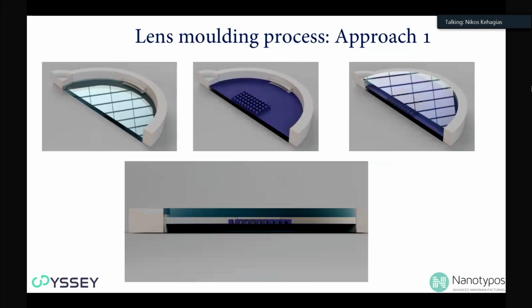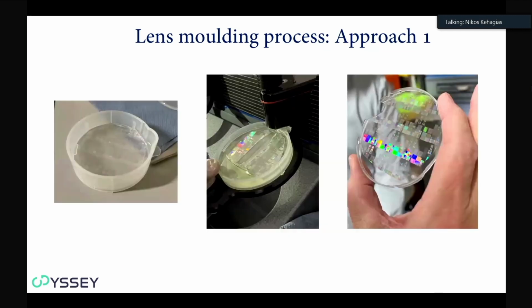This is just a cross section of having 2 glass molds, our patterned film, our working mold, inside which has a spacing, so we can control really the thickness and correct and replicate by this simple molding technique the nano features on our UV curable resist. So this is just some images of the process, how it was filled, the rubber ring, and how we are filling in the UV material.